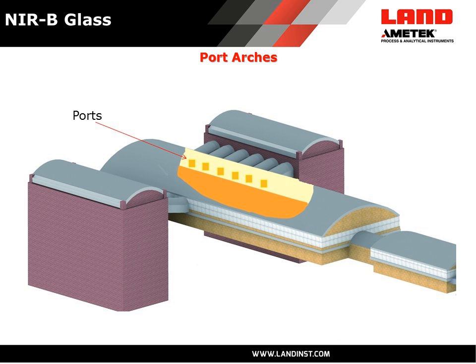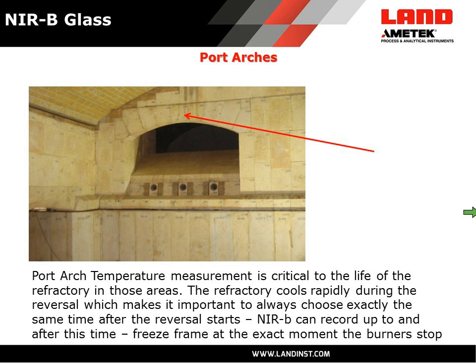So now let's look at refractory temperatures themselves. And some of the areas within a tank that are very, very critical are the ports themselves, the areas around the ports, and particularly the tops of the ports, known as the port arches. And so here we can see on a newly lined furnace, this is an end-fired one, this is typically the area that would be measured on a reversal,